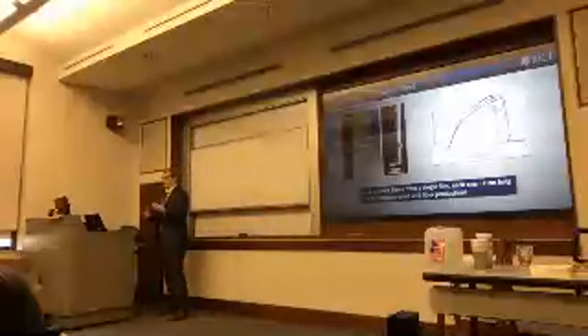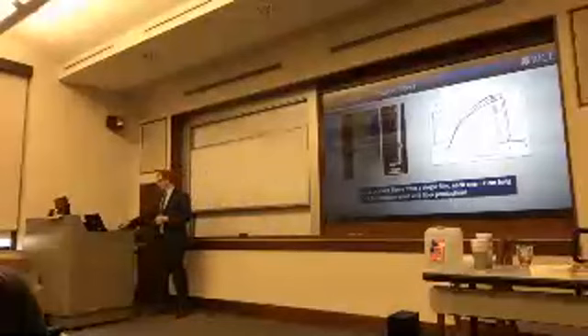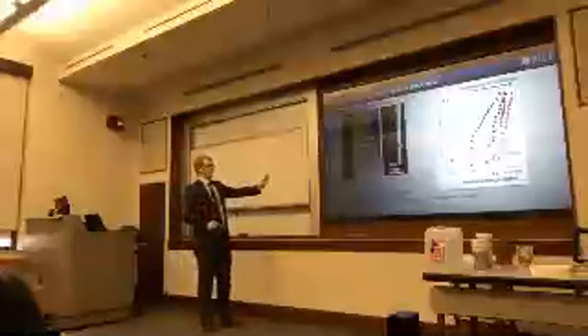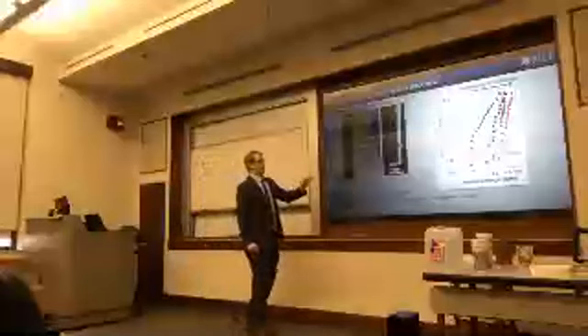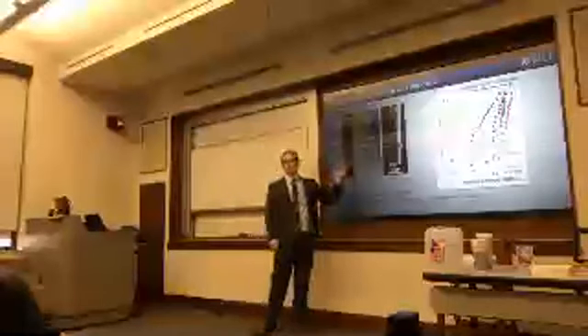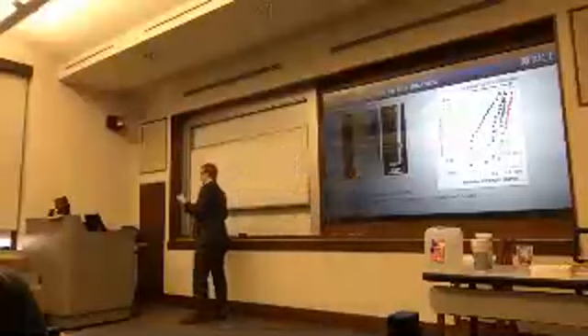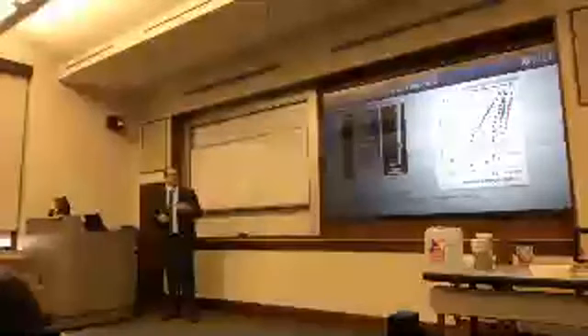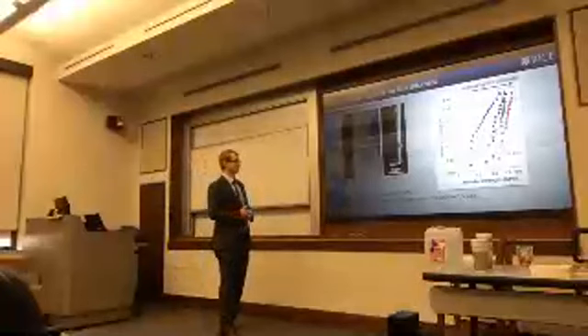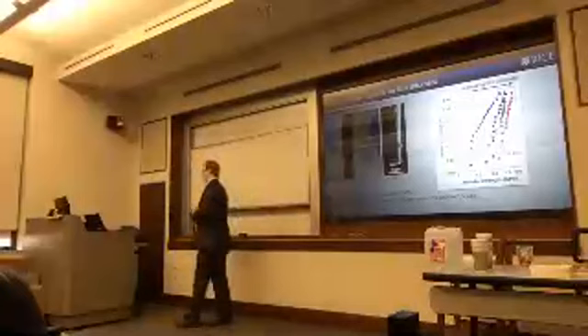Now at this point, it's not clear how we optimize our fibers or what processing parameters optimize the fiber properties through this method. So to investigate that, we're going to look at the dependence of the fiber tensile strength on the thickness of the film that you produce. Here I'm plotting the tensile strength for multiple fibers peeled from 5 different films, ranging in thickness from 1.7 micron to 0.4 micron. The nominal tensile strength for fibers produced through these different films increases from 1.5 gigapascal all the way to 2.8 gigapascal as you decrease the film thickness. So what this tells us is that the optimized or the highest tensile strength we can achieve is actually by using a thinner film.